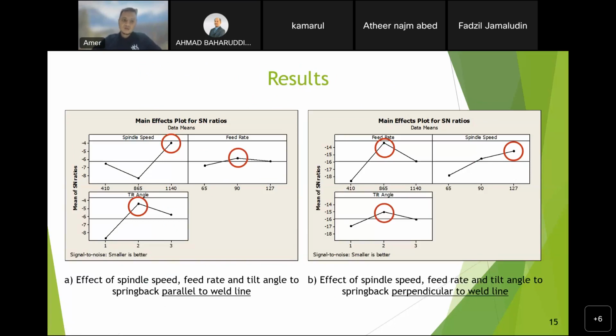As you can see, it was discovered that the best parameters for both springback outputs are different, as referring to figures A and B. From the graph, the best parameter for the springback parallel to weld lines is 1140 rpm for spindle speed, level 3, 90 mm per minute feed rate, level 2, and 2 degree tilt angle, level 2. And the best parameter for perpendicular to weld lines is a feed rate of 865, level 2, spindle speed 127, level 3, and tilt angle 2 degree, level 2. So different parameters for different weld lines.